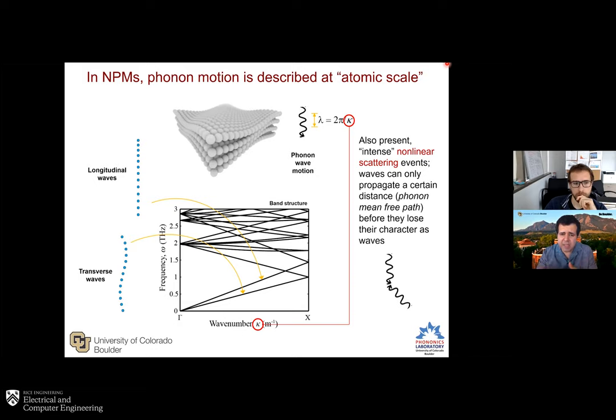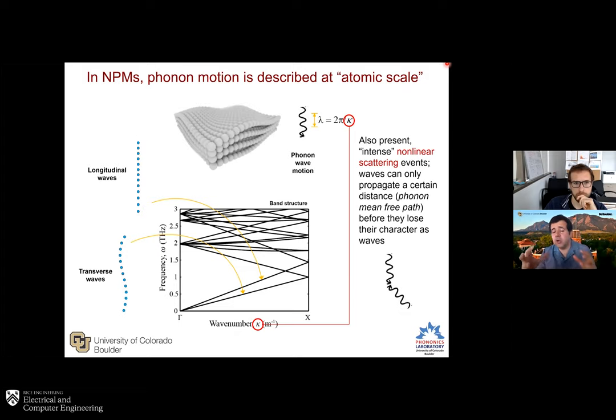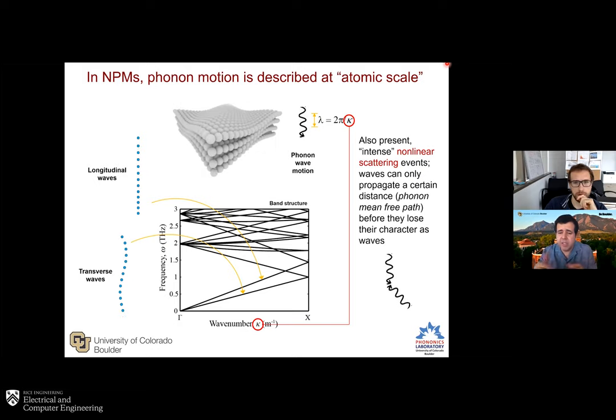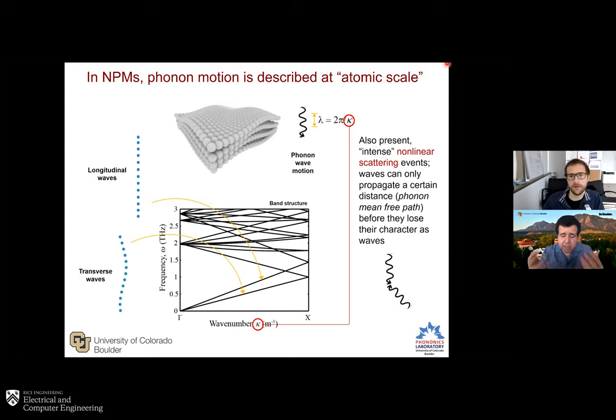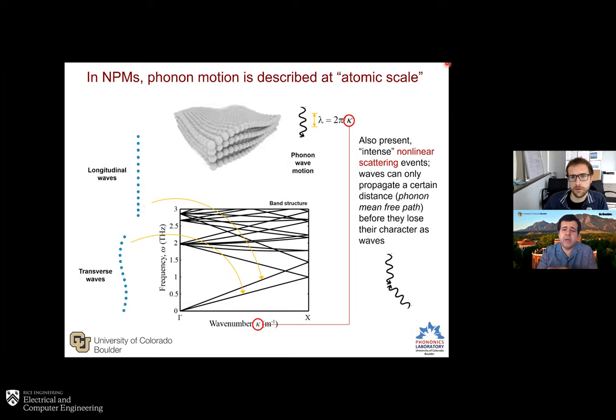And the scattering mechanisms, just like I was saying earlier, you could have scattering from obstacles and so on, but you also have, and this is very fundamental, scattering due to phonon-phonon interaction. So that's characterized by the phonon mean free path. And interestingly enough, and to our benefit, for silicon specifically, the phonon mean free path tends to be quite large. So this provides us with quite a decent window of opportunity to use notions of waves and band structure, especially if we can manipulate these waves to control the thermal transfer because of these large mean free paths. And I'm going to talk about that in more detail shortly.